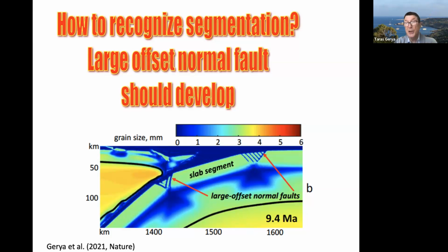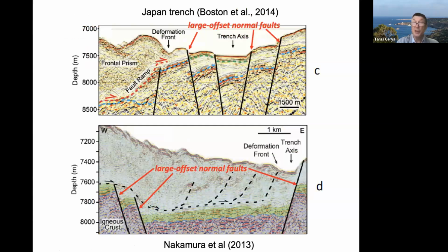So one of the enigmatic observations that needs to be explained is the presence of these large offset normal faults. Large offset normal faults, when they are present at trenches, imply that instead of distributing the bending-related deformation evenly, we focus it in one place. And what is the reason for such focusing? One possible explanation is that we have this feedback from the grain size reduction exactly in the place where strain weakening of the fault is happening, and therefore we have this very strong focusing of brittle deformation and the development of large offset normal faults. And such large offset normal faults are systematically present at trenches, however, not at all trenches.